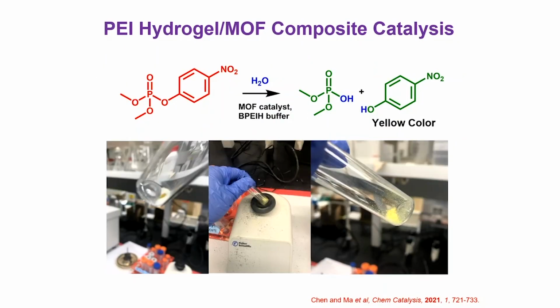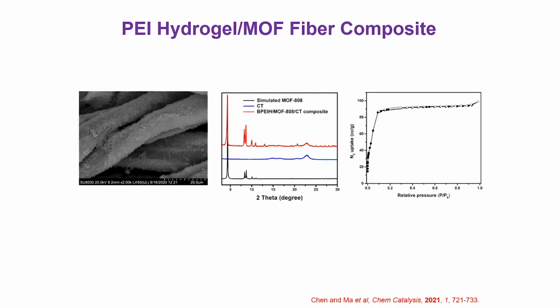Kai, in this case, we told him to just test it before we put it on fibers and textiles, because that takes time. Does this work? Your product is yellow, your starting material is clear, and what he showed is that as soon as he dropped the starting material and it touched the solid, it turned yellow instantaneously. So we knew we really had a composite that is very quick. It doesn't require a 12-minute half-life. This is almost instantaneous. And at that point, we went and put this on the textile.